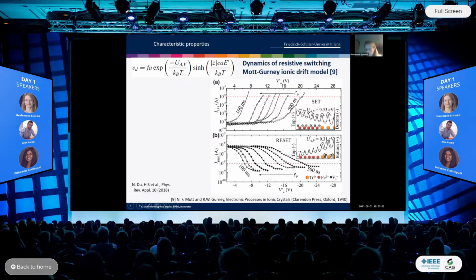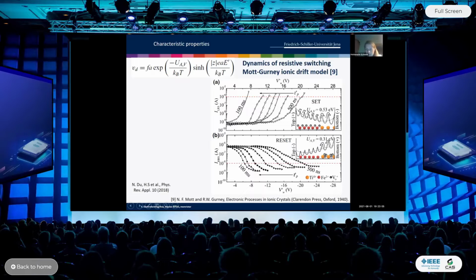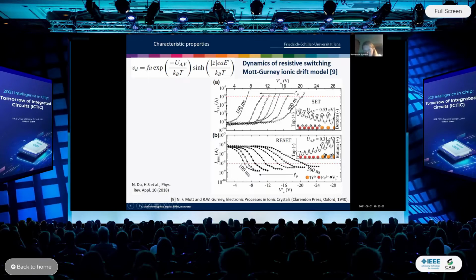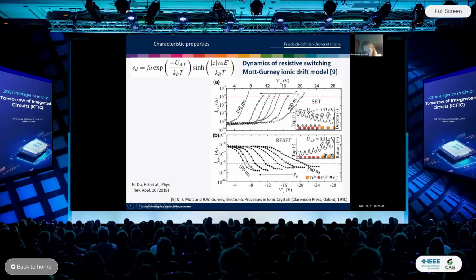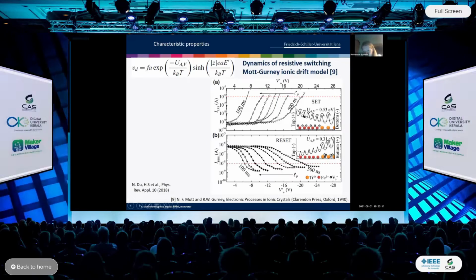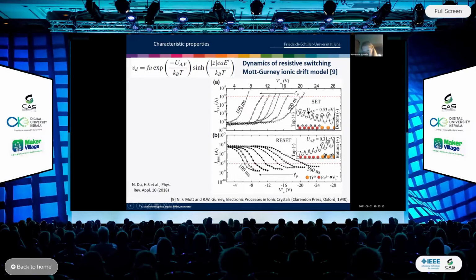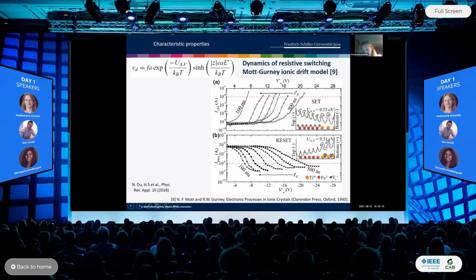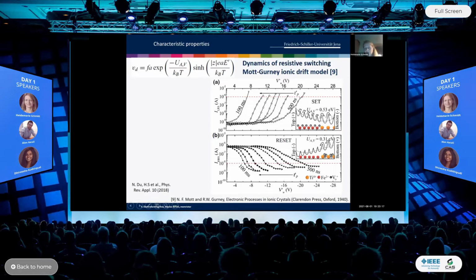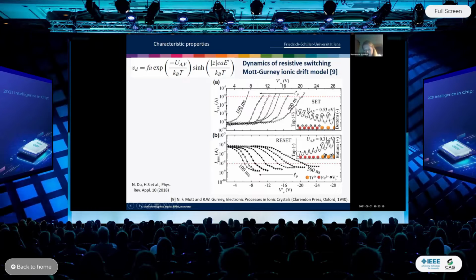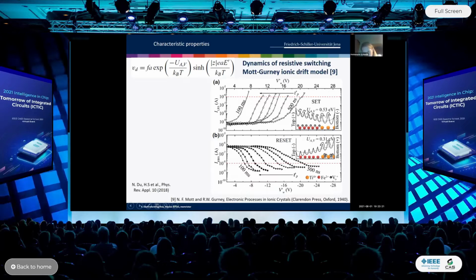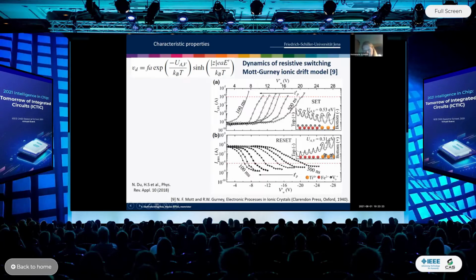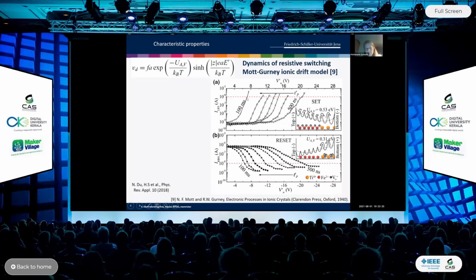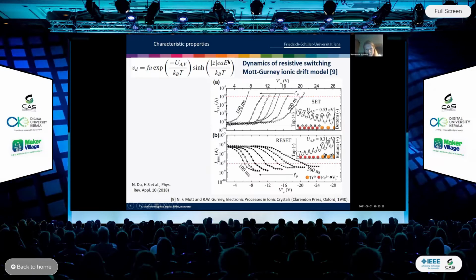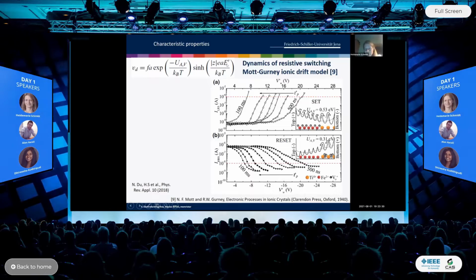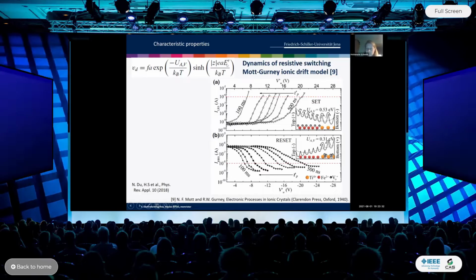And then we know if we apply a positive writing bias, then the oxygen vacancies will drift from the top electrode to the bottom electrode. This is shown here. This is the direction of the drift of the oxygen vacancies under application of the positive writing bias, and this barrier has to be overcome. In addition, the amplitude of this writing bias determines the electric field, which is labeled here with E prime.